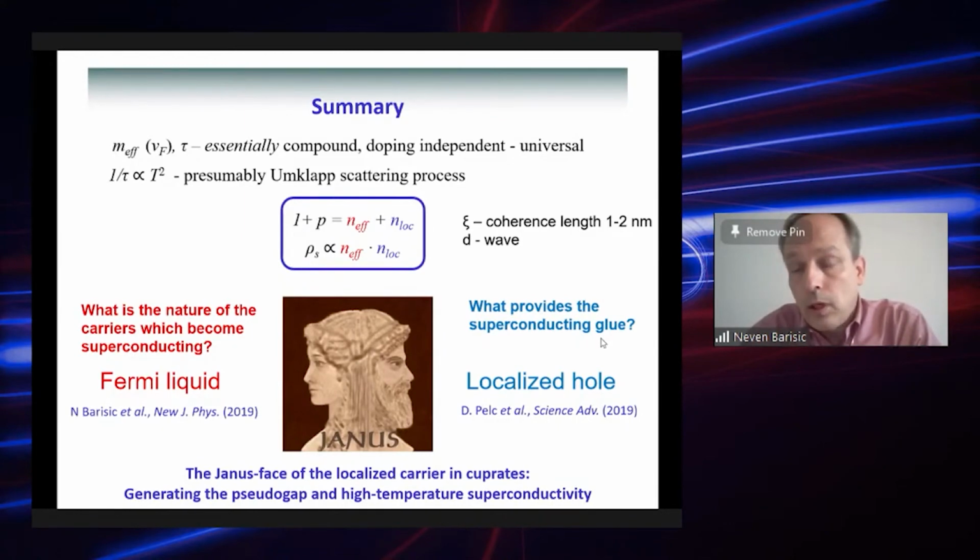I mean, phonon probably surely has a role in localization, to my understanding and my knowledge, which may not be so big as yours, but Umklapp process, in fact, promotes the Mott state. To get the Mott state, you need to have a strong Umklapp. And as you can see, we do have strong Umklapp because all the scattering is dominated by the Umklapp processes. We say that you have 10 electron volts on this position from Hubbard U, and many people agree that this parent state is the Mott state where the two charge carriers lock themselves due to the Hubbard U. Okay. I don't have any other arguments, and I don't mind it's different.